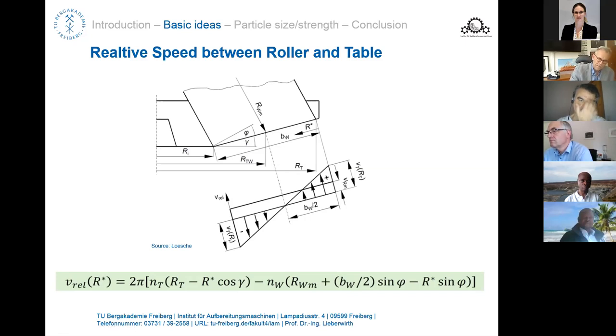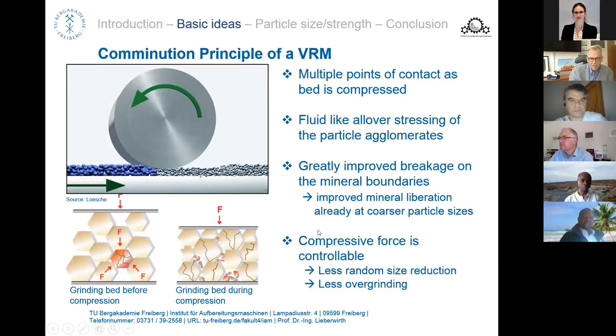For all crowned type rollers, you have even more complicated schemes. Particularly on the sides, you have much more shear there, which is a disadvantage if you have very abrasive material. But if you go for the original application of vertical roller mills, which was coal grinding, you wanted to achieve very fine material with least effort. And in coal grinding, you have material which is not very abrasive. So for coal grinding, the crowned rollers are certainly preferable compared to flat or conical rollers or even cylindrical rollers, which are nowadays also in the market. So the relative speed makes a major difference between the HPGR and the VRM. That needs to be kept in mind considering the difference of the two mills.